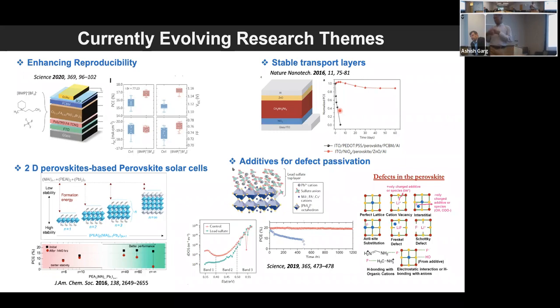Other approaches: perovskite thin films tend to have a lot of defects. Defects are hungry places for eating away your holes and electrons. So how do you passivate those defects? The concept is very similar to what you saw in amorphous silicon, where you put in hydrogen to passivate the defects. Here you use different kinds of additives. These could be organic additives, inorganic additives, different compounds which sit in traps and basically passivate the traps and grain boundaries in these materials. So different sorts of models are possible. You can have point defects, grain boundary defects, or microstructural defects that can lead to passivation. And depending upon what you use, additives can actually make solar cells last fairly long as compared to the ones which don't use additives.